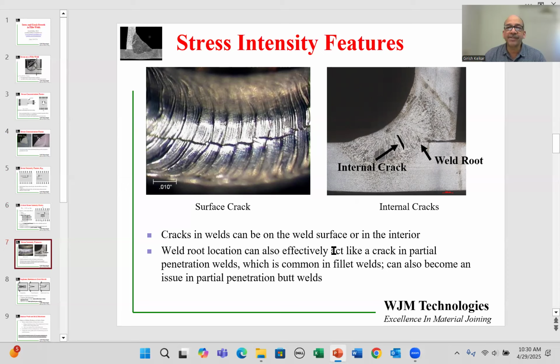So weld root is common in fillet welds because fillet welds very rarely are welded full penetration. So there is always a weld root in most cases. But this can also be true in butt welds. In partial penetration butt welds, we can also have a high stress point at the edge of the weld on the root side.